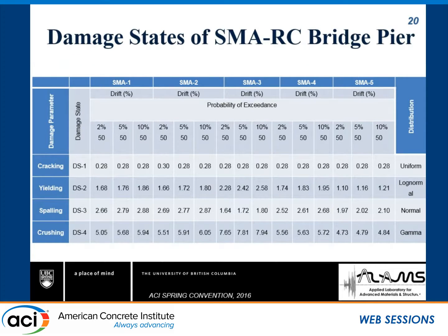We performed incremental dynamic time history analysis giving base shear versus drift for each SMA type, with 200 data points per curve. The red curve is the median, with 5th and 95th percentile bounds shown. For cracking, since the cross-section is the same for all, they all show almost the same cracking drift, following nearly a uniform distribution. For yielding, the two nickel-titanium alloys show similar drift levels. SMA-3, with a much higher FY value of about 700 MPa compared to 200–500 MPa for others, requires much higher drift to reach yielding. SMA-5, with modulus of elasticity about half of steel, reaches yielding much earlier. Yielding follows a log-normal distribution.